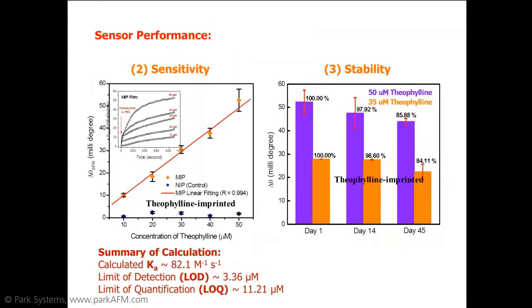Sensitivity and stability are demonstrated by these two plots. Sensitivity is showing a limit of detection of 3.36 micromolar, and a limit of quantification of about 11.2 micromolar. What is important here is that we have a linear calibration based on concentration. On the right hand, you have the stability of the detection that was done even up to 45 days. In other words, we only see a 15% reduction in the sensitivity and selectivity even after 45 days.